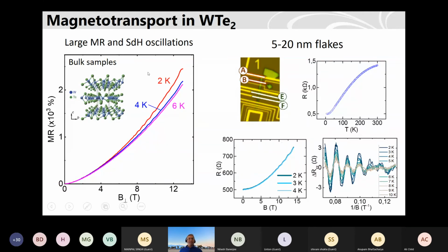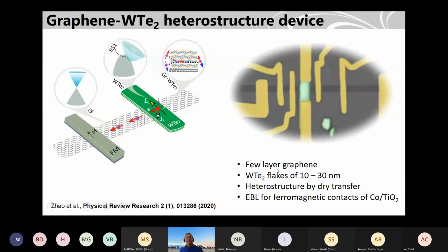So we also see similar things in this bulk sample. And we also make very thin layers, up to 5 nanometers, and we see metallic conduction. We also see the Shubnikov-de Haas oscillations at high magnetic field. So we can find the carrier mobility, which is around 10,000 at low temperature, so which is a good material.